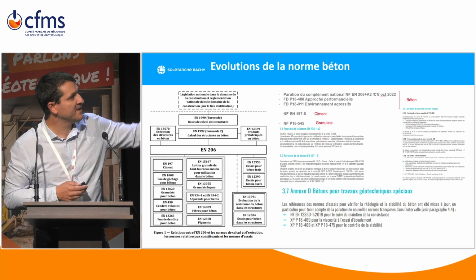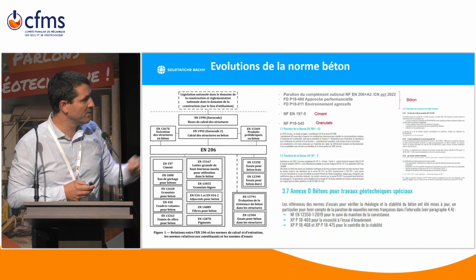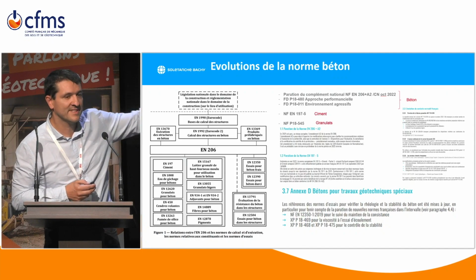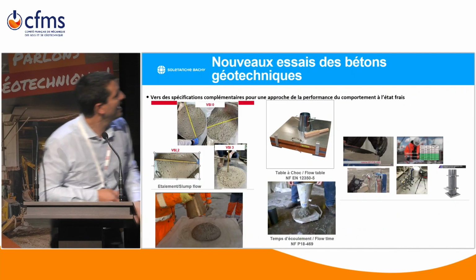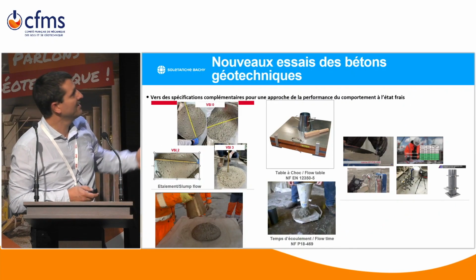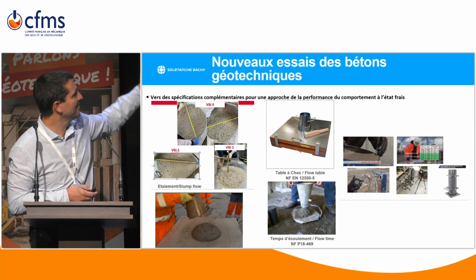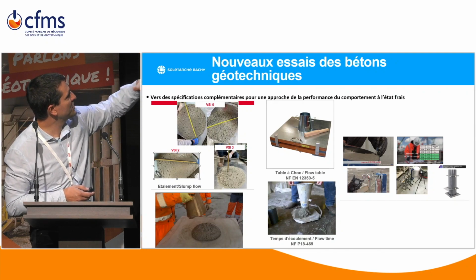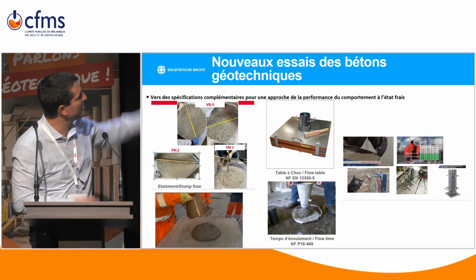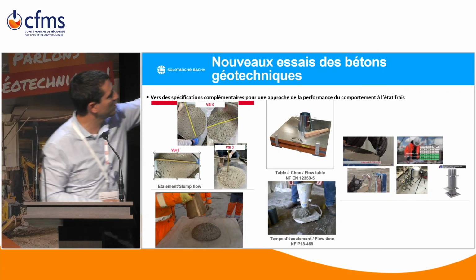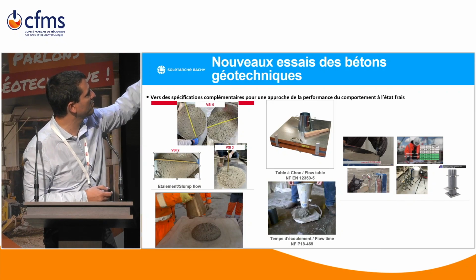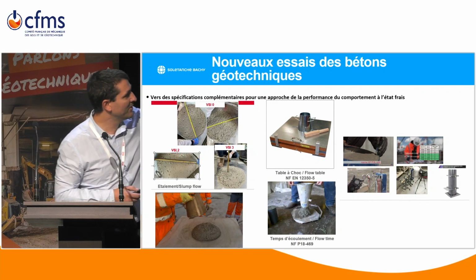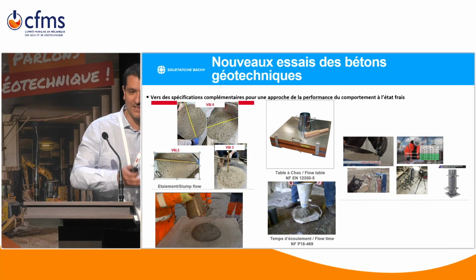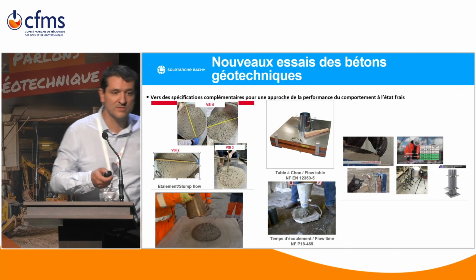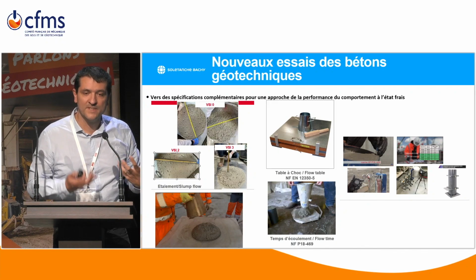And specifically for geotechnical concrete, we have added the additional tests that have been passed into standard. Those tests mainly are the flow table, the slump flow, which allows you to have a direct vision of the stability of the concrete, detect whether or not the concrete is segregating. The flow cone, like the flow cone for grouts, just measuring the time to empty an Abrams cone to get a feel for the viscosity of concrete.